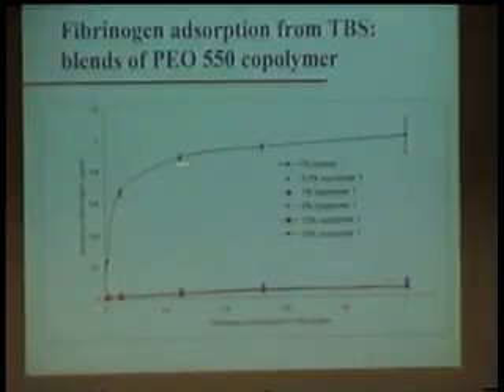The protein adsorption rises up pretty rapidly and levels off around 1 microgram per square centimeter. That translates into a pretty tight layer of fibrinogen where the surface is pretty well covered with a monolayer. As soon as you start to introduce a little bit of this copolymer into the blend, your adsorption shoots way down. Even at the level of 0.5% by weight, you've lost about 95% of your protein layer.